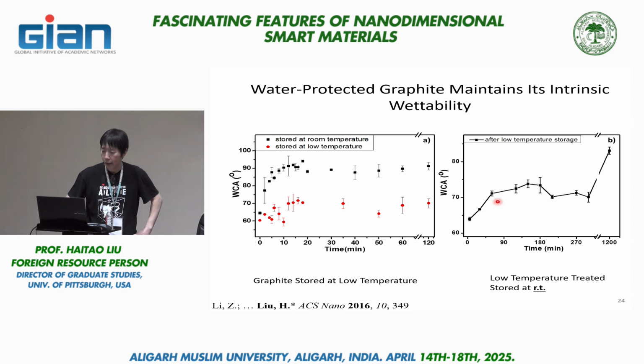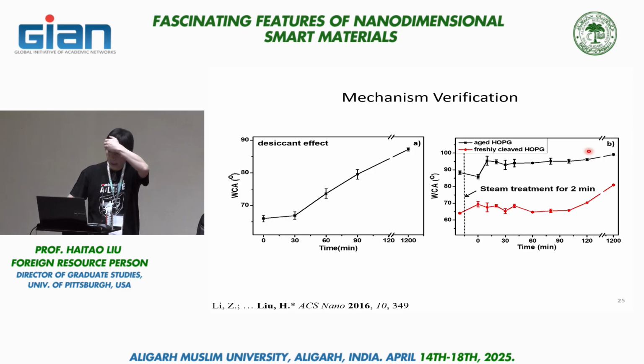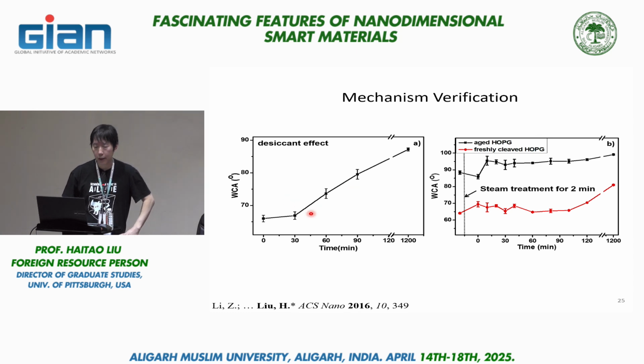We also look at an experiment where we store it at low temperature, and then we move it to room temperature, and quickly we see this increase in the water contact angle. So it seems to suggest that low temperature storage would slow down the adsorption of hydrocarbon and make the surface remain in a hydrophilic state for a much longer period of time. We confirmed this is not a temperature issue, but rather a humidity issue. And this can be shown by looking at the desiccant effect, meaning that if we expose the graphite to a dry environment, the contamination seems to be faster.